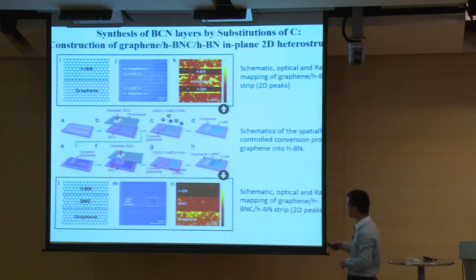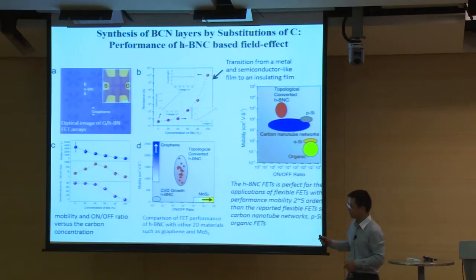And what is more interesting is that if the concentration of boron nitride is 40%, then we can get a maximum on-off ratio up to 1K, and the mobility is also around 1 to 2K. So comparing with molybdenum sulfide, its mobility is pretty high, and comparing with graphene, we get a much higher on-off ratio. So this material may have some possibility for electronic devices. I won't say it will beat silicon, because we have a lot of work to do to improve it. And we also compare it with different thin-film FET materials like organic, amorphous silicon, and carbon nanotube networks. So these are the materials, and this is what we can make.